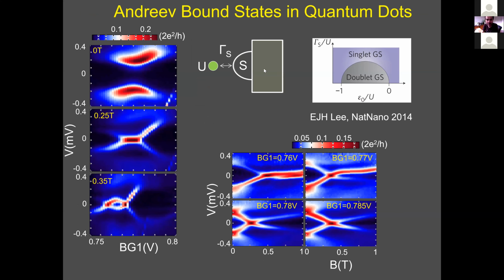So this is how it looks. Again, this is a phase diagram, and this is actual data from my lab. These spectra are Andreev spectra, and so you can see at 0 magnetic field, as a function of gate, we have these states that never reach 0. That's because we're here in a singlet ground state regime. So when we change the charge occupation of the dot, we always stay in singlet. We are here at strong coupling.